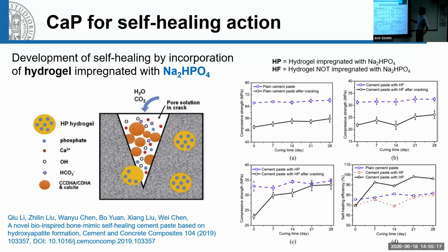So for instance, here you can see the compressive strength of concrete when it contains the hydrogel with the phosphate precursor. There's a progressive increase in compressive strength when you induce cracking and release of the phosphate precursor. So in this study, it was demonstrated that it's possible to recover the mechanical properties of compressive strength thanks to the healing action of the new calcium phosphates that are formed through this mechanism.